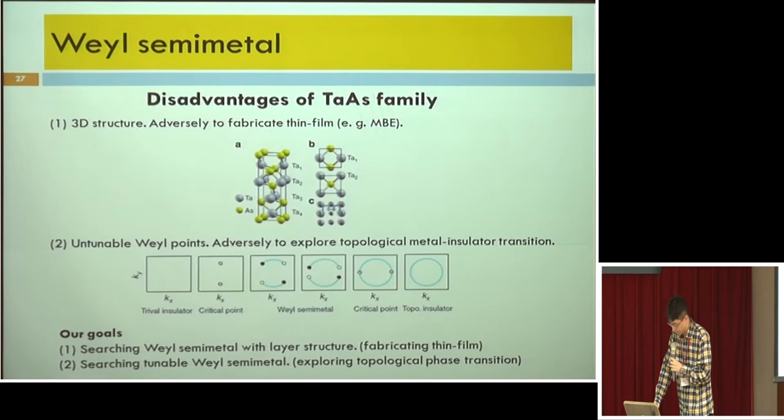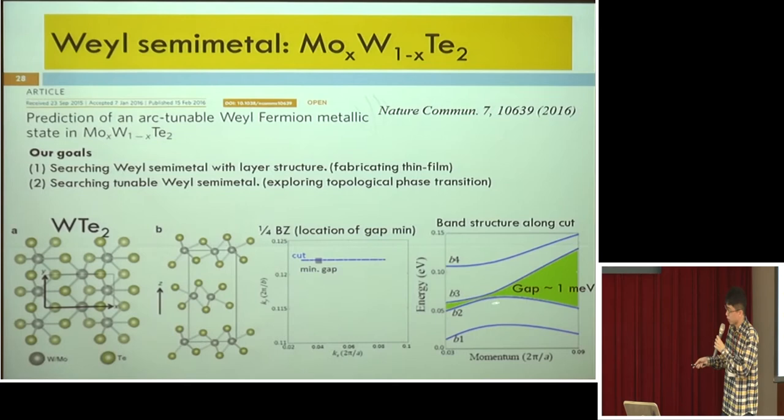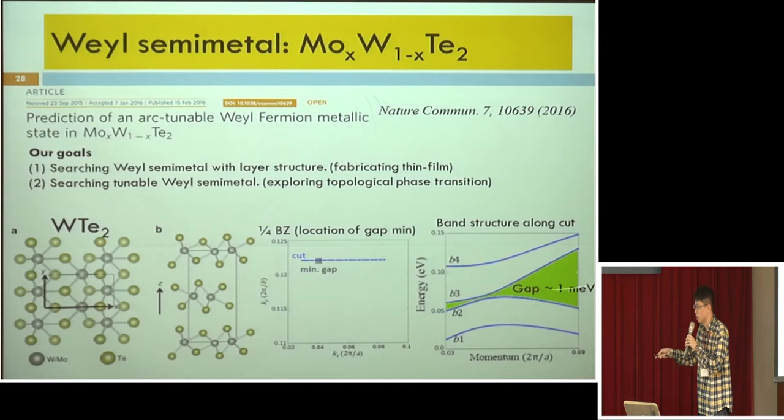In 2016, we noticed tungsten ditelluride. Tungsten ditelluride has a layered structure, and this is its band structure. But unfortunately, tungsten ditelluride is an insulator. There is a gap here. The gap is very, very small, around 1 millielectron volt. So this result implies that even though tungsten ditelluride is not a Weyl semimetal, it is very close to the phase transition boundary. If we can find a way to make the B2 and B3 bands cross, we can get a Weyl phase